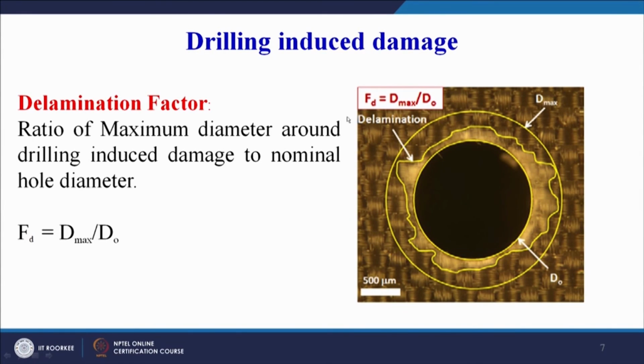Then there is drilling induced damage all around the hole. We can quantify this with the help of a delamination factor. So FD, we can see Dmax. Dmax is the maximum area or the diameter of the maximum area around the hole that has been damaged, and D0 is the original diameter that we planned to make, or the original diameter of the hole that was our objective. So delamination factor usually is defined as the maximum diameter around the hole which has been damaged, and D0 is the objective or the original diameter that we planned to make. So the ratio of the maximum diameter around the drilling induced damage to the nominal hole diameter.